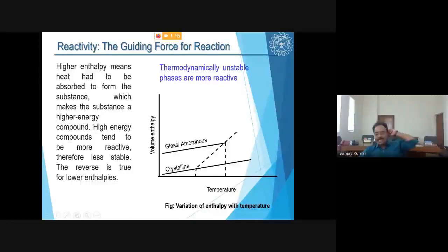If you see the law of thermodynamics, unstable phases are more reactive. So glass is less stable than the crystalline. So glass or amorphous phases are more reactive than the crystalline. If I take a material which is crystalline, say for example quartz, and I take the same composition material which is amorphous, like quartz glass, the reactivity of the amorphous will be higher. And this is because of the high volume enthalpy in the glass or amorphous phases and low volume enthalpy in the crystalline phases.